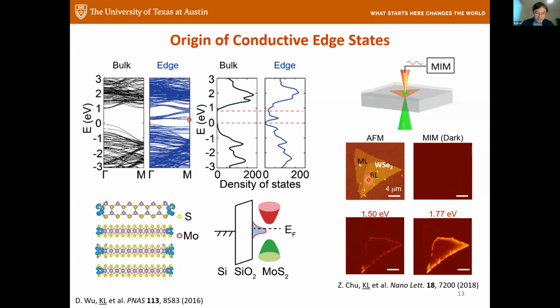Thanks for the question. In the paper, we also had a postdoc in Allan MacDonald's group helping us calculate these in-gap states, where they are. First of all, the bilayer has a smaller band gap compared with the monolayer, and the position of those in-gap states is also lower in energy. That's why as we shine the laser, those are the regions that get bright first. So that means the trilayer could possibly have even lower. I believe so.